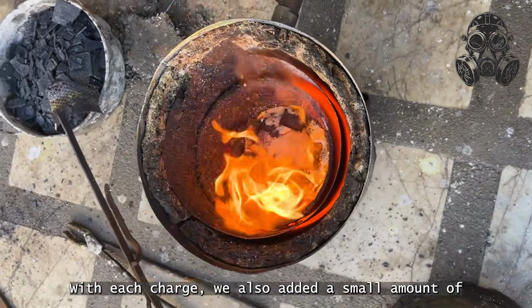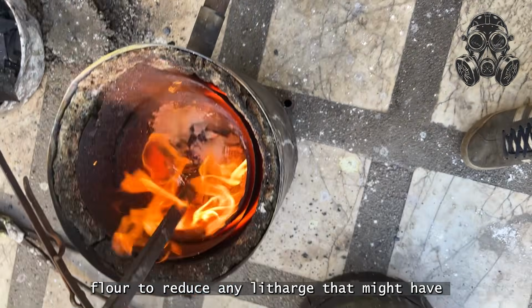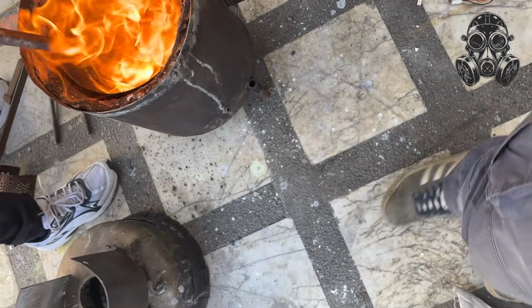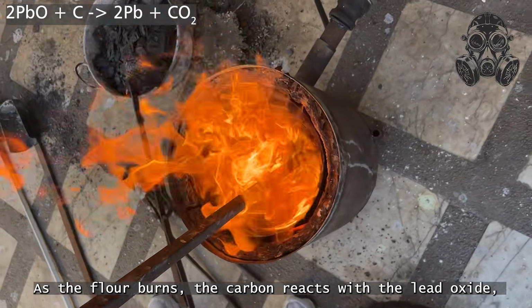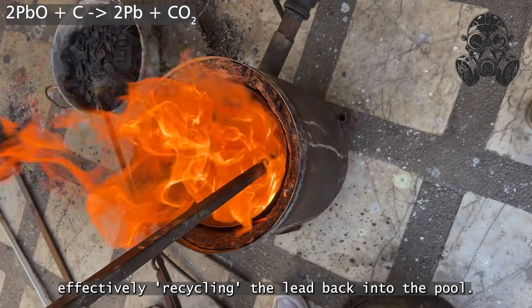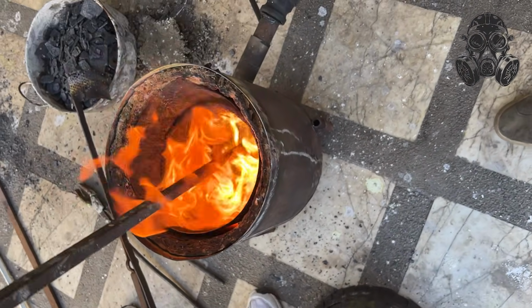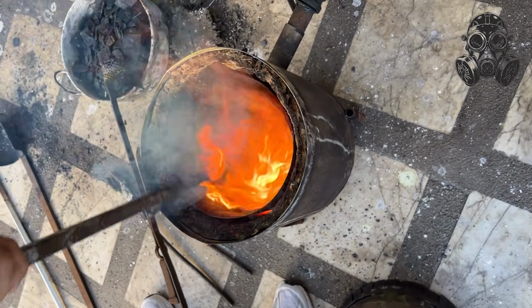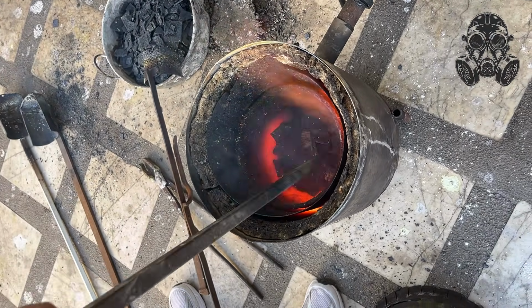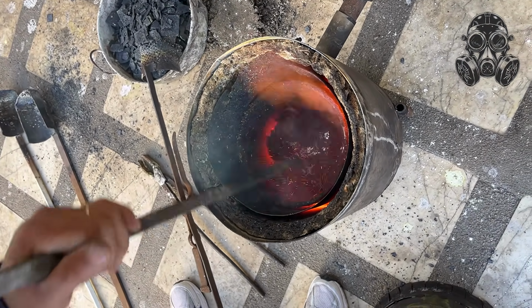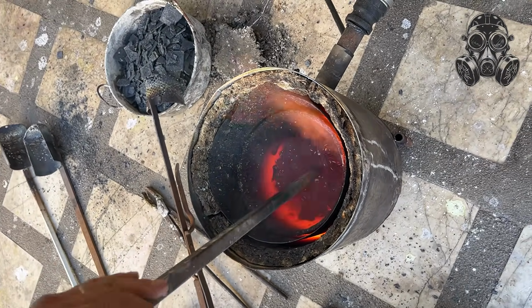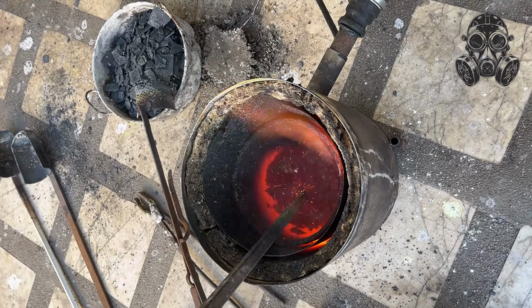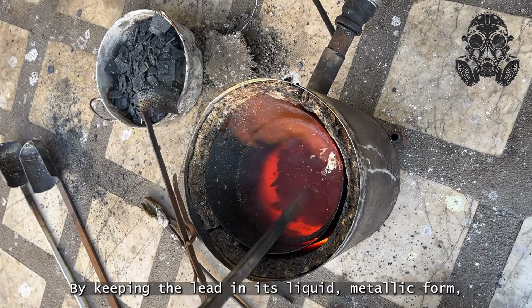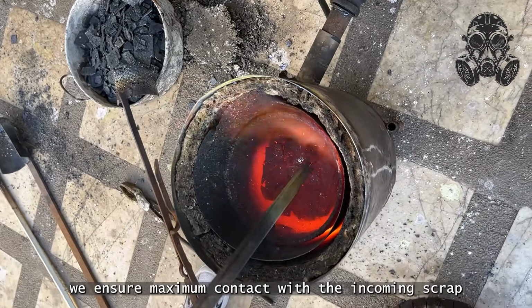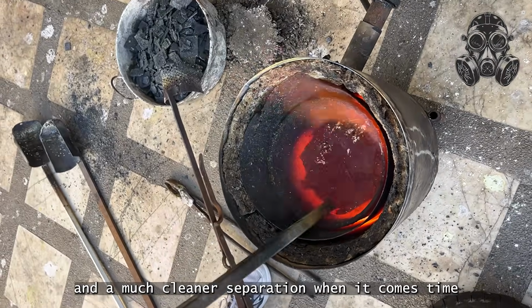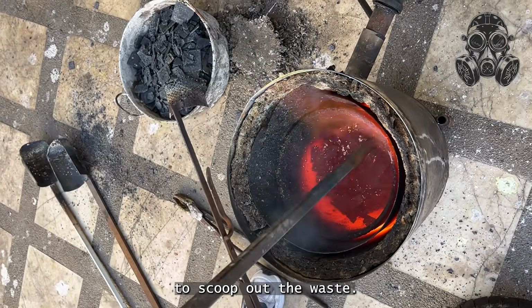With each charge, we also added a small amount of flour to reduce any litharge that might have formed back into metallic lead. As the flour burns, the carbon reacts with the lead oxide, effectively recycling the lead back into the pool. By keeping the lead in its liquid metallic form, we ensure maximum contact with the incoming scrap and a much cleaner separation when it comes time to scoop out the waste.